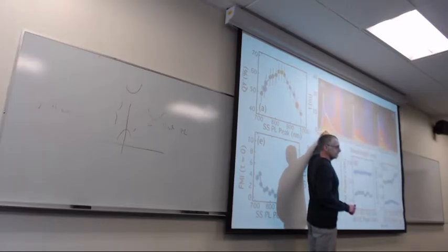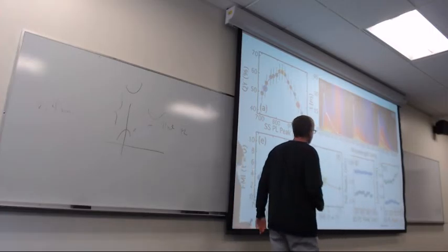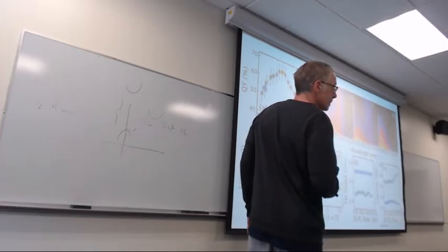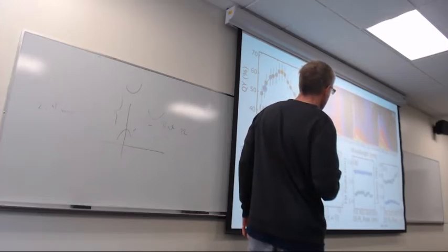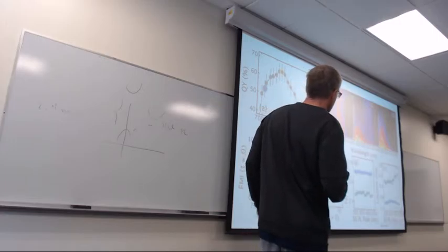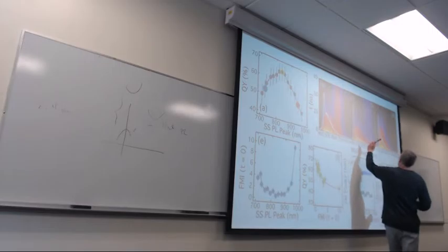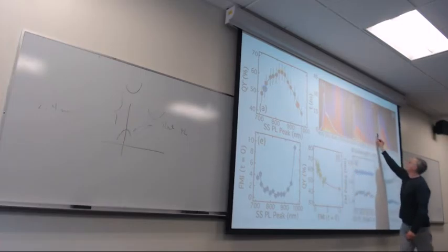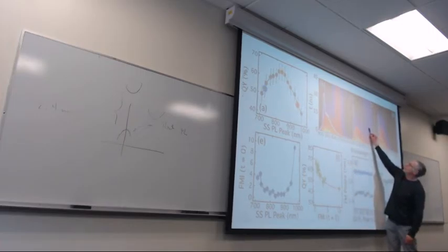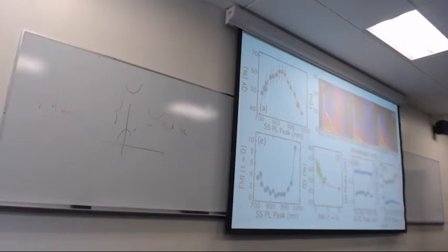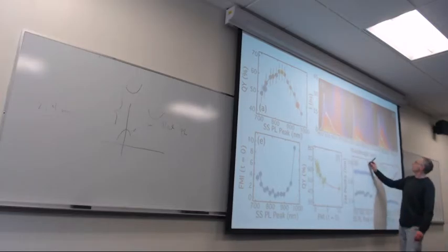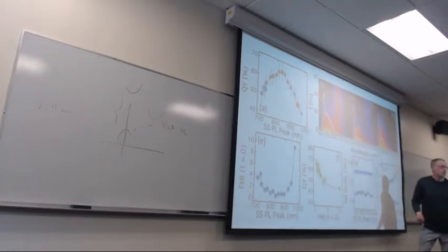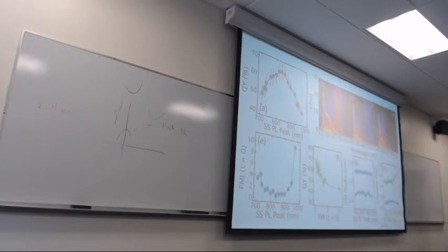Okay, but just a second. On the red case, it looks like this bluish, reddish area around 700 is not there anymore, right? That's because the nanocrystals are getting bigger as we go left to right, and the red PL peak is moved off scale. You can just see it here. So you think it's appearing at more than 800 nanometers? Oh yes, you can see right here. This guy's at 950.